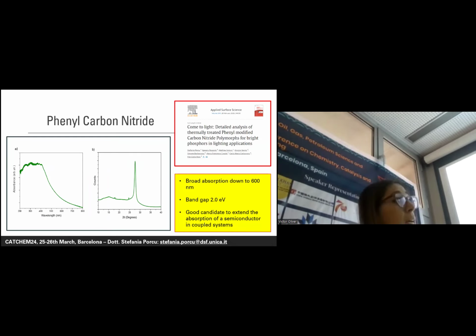We deeply characterized this material because, as I said before, it was not known in the literature. Due to the time for this presentation, I cannot go into depth explaining the whole polymerization process or all the materials we studied, but I will focus only on the one we found very interesting for photocatalytic application. We studied this phenyltriazine, which we call phenyl carbon nitride, from both structural and optical points of view. Here in this slide, I am showing an absorption spectrum of this material, and as you can see, the absorption starts more or less from 600 nanometers.